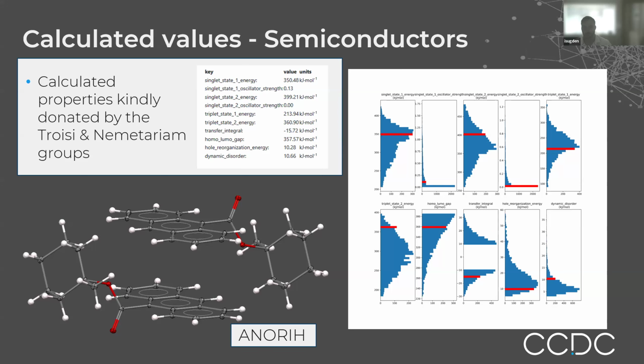So the most obvious calculated property that's relevant for semiconductors is the HOMO-LUMO gap. So if the energy difference between the highest occupied molecular orbital and the lowest unoccupied molecular orbital is in the range of visible light, then that suggests that you have a potential organic solar cell component. It's able to absorb light in that region. Transfer integral then is giving you an indication of if it is able to have an excited electron because of absorbing visible light, is it able to then transfer that excitation to the next molecule along? Is it able to propagate the excitation?